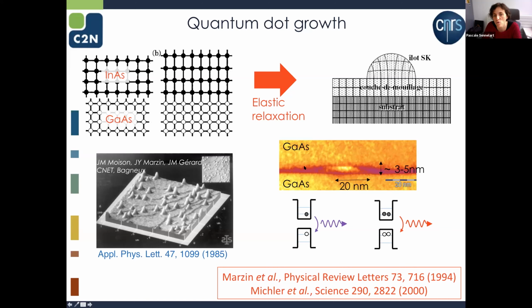So you end up, then you grow again gallium arsenide, and you end up with these 20 by 3 to 5 nanometer traps for carriers in the three directions of space. And these are really the quantum well in the three directions of space that we study at school, and you have discrete energy levels. So when you create one electron hole pair or two electron hole pairs in this system, because they are trapped in a very tiny volume, they don't emit photons at the same energy. And this is how we found out in 2000, it was shown by the community that you can have single photons emitted by this kind of atom.